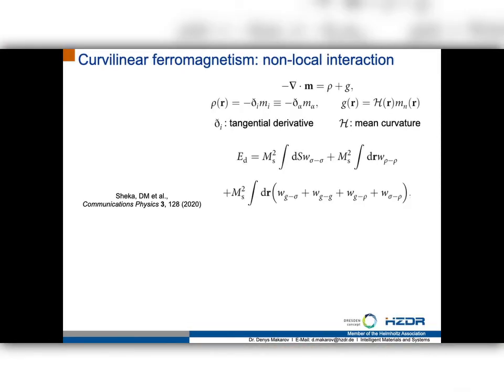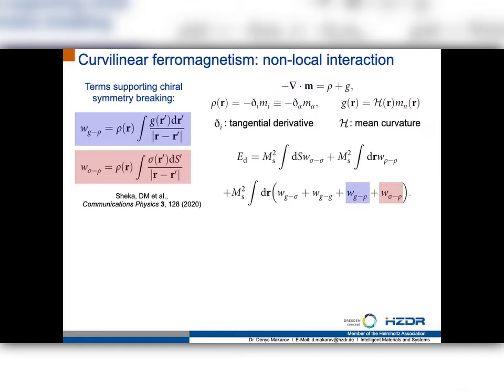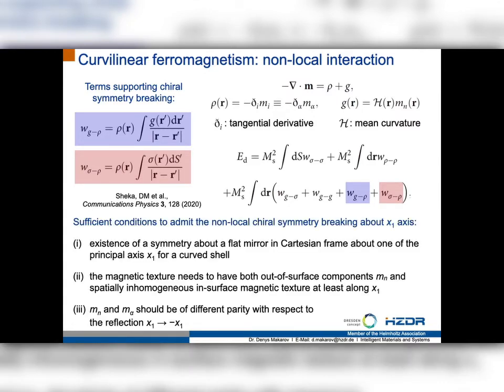Where does it come from? If you analyze this non-local part of the magnetostatic energy, you will see two terms which can support chiral symmetry breaking. This is an interaction between surface and tangential charges and geometric and tangential charges, which can allow you to observe the non-local chiral symmetry break.